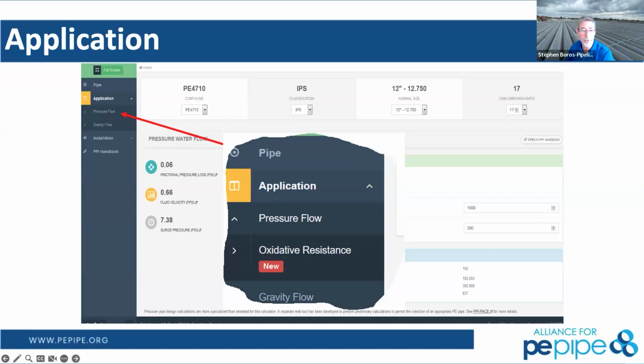I've been doing this for a long time. Back when there were a few instances where polyethylene over time did end up failing, it was determined that it failed because of oxidative degradation, which embrittles the material and causes small cracks to occur. So when you go back and investigate that, we found that it happened for two main reasons. First of all, you had a very aggressive water situation, and you had high annual operating temperatures, such as in the desert in Arizona, Las Vegas, things like that, more shallow burial situations.